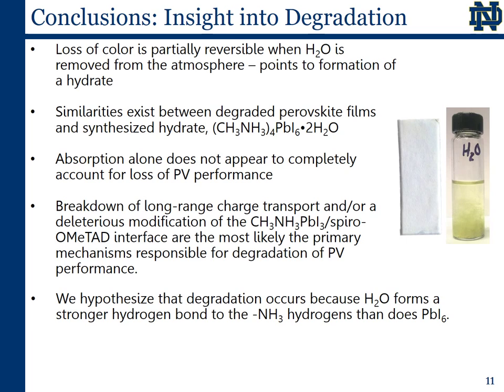Finally, we hypothesize that the degradation of the perovskite structure of methylammonium lead iodide occurs when the water is able to form stronger hydrogen bonds to the ammonium hydrogens than to the lead iodide octahedra. Controlling this process and determining ways to slow or even mitigate this reaction between methylammonium lead iodide and similar hybrid perovskites and water will be crucial to their eventual implementation in commercial solar cells.